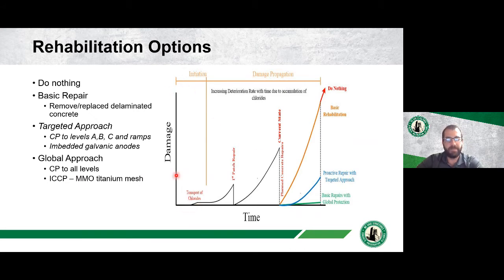We begin when the structure is brand new, and then over time we start to have some deterioration. And they went out and did some first repairs, brought the delamination deterioration down to close to zero, but they really didn't stop or preserve the structure. So that deterioration slope continues on, right? We continue to deteriorate the structure because we only repaired what was physically damaged at that time. We didn't do anything to ultimately slow down or eliminate the corrosion aspect.